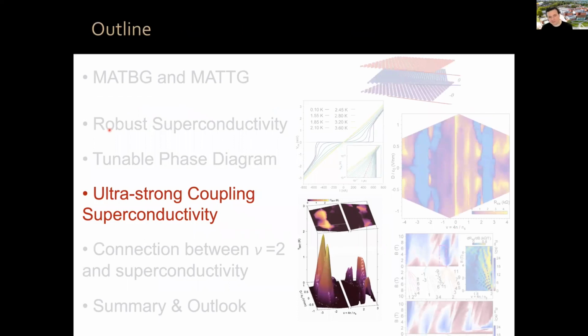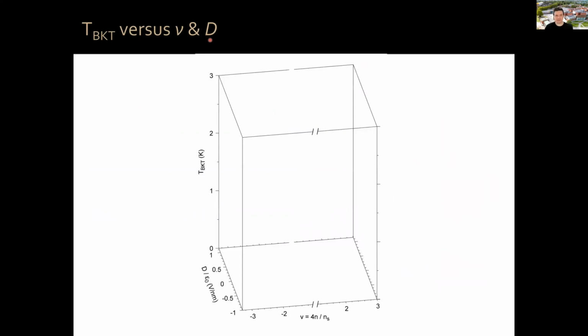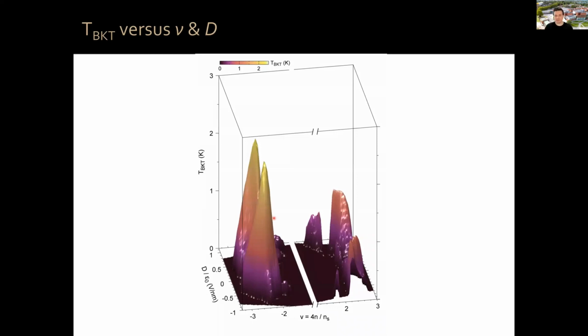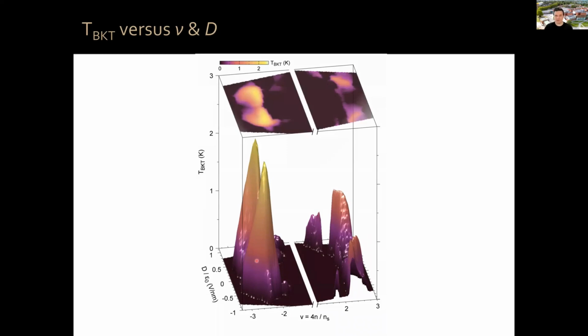Let me tell you now about the coupling strength of this superconductivity, okay? The normalized coupling strength. If you measure the TBKT versus filling factor and versus transverse displacement field, we can have this three-dimensional plot of TBKT versus D and nu. I'm eliminating the middle part where it's not superconducting, focusing on the superconducting regions. As you can see, it's highest between -2 and -3, and then between 2 and 3, and also some inner branches, okay? This is sort of similar to magic angle twisted bilayer graphene. This is also the strongest superconducting dome between -2, -3, okay? If you project this into this plane, you can see the strength of TBKT in this map, okay?